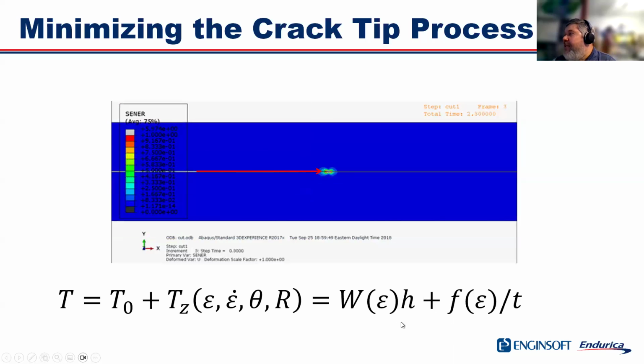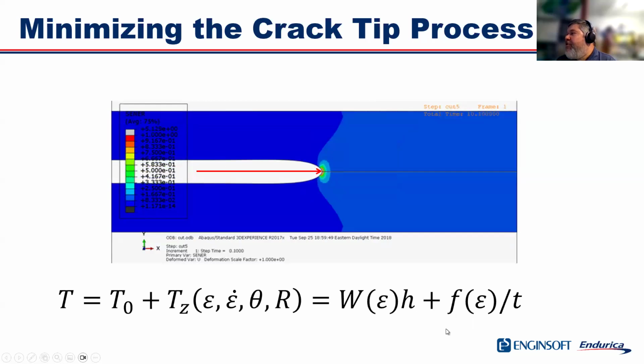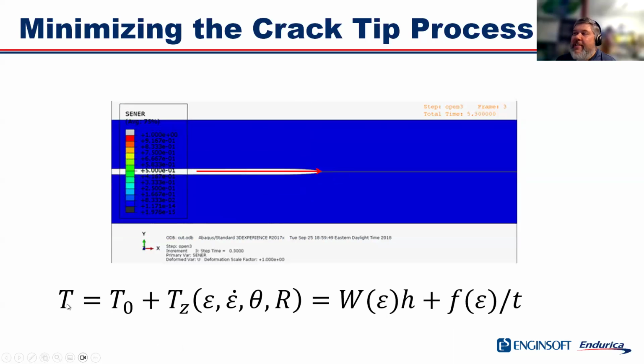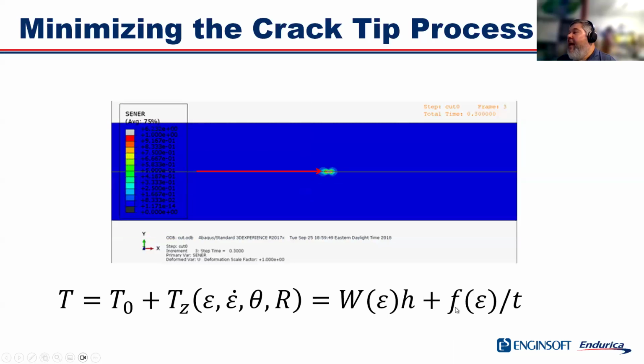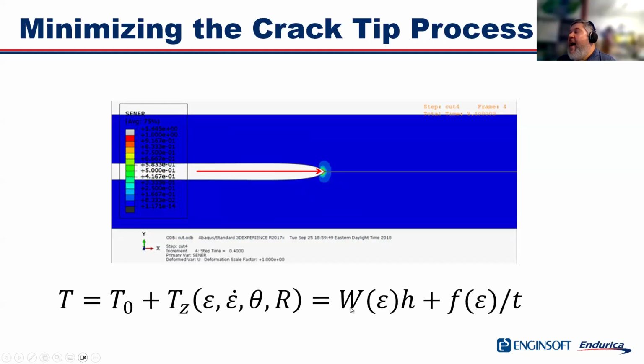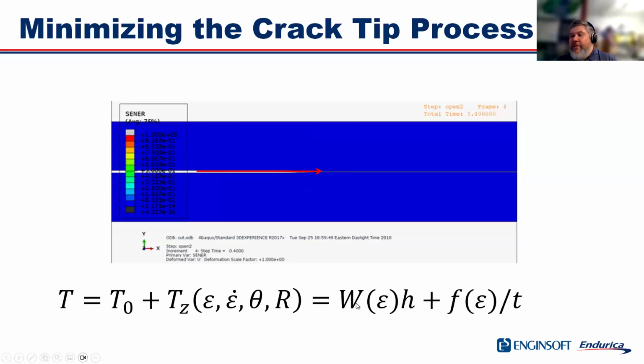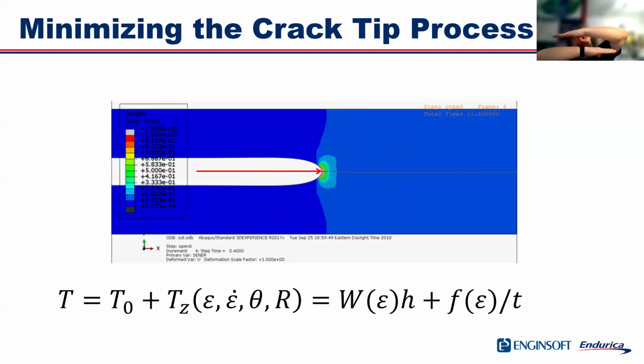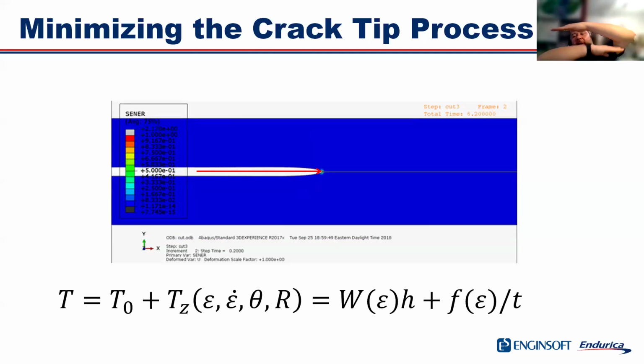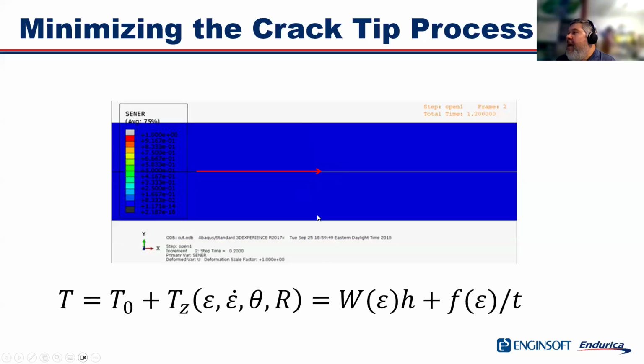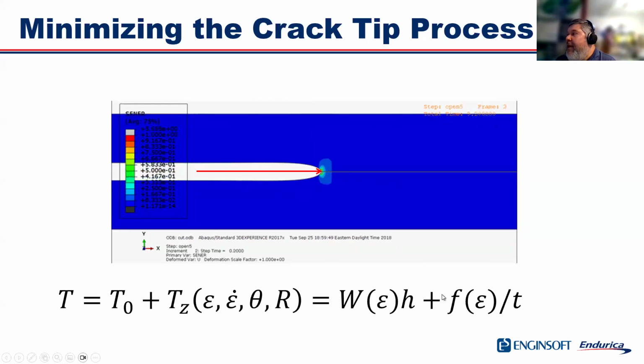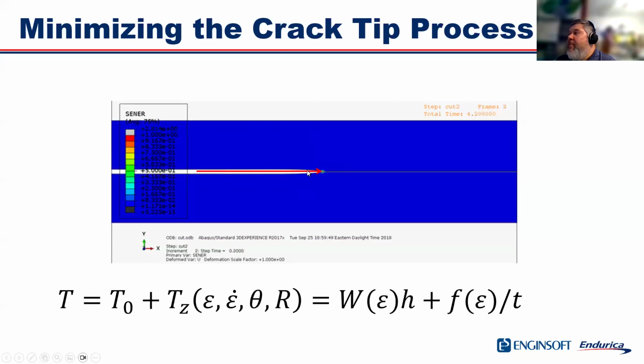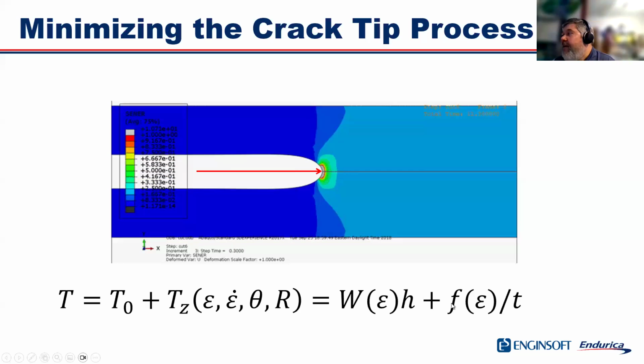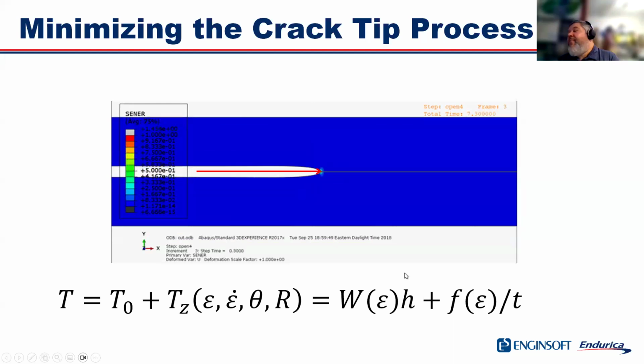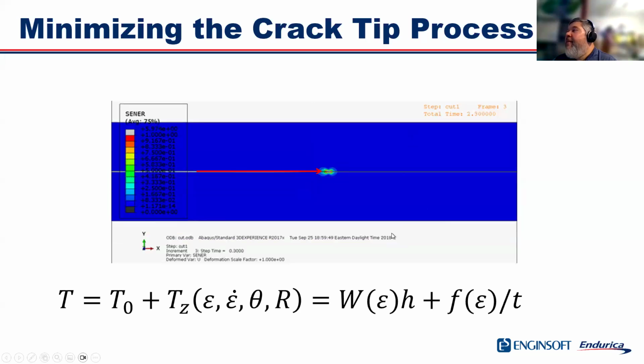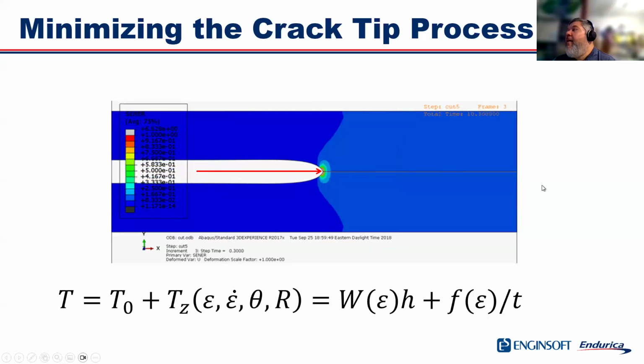Now you'll notice here I've got another equation to the right that's got two terms. This is an equation that expresses the tearing energy in this experiment. The first term is the tearing energy that the crack experiences due to the opening of the crack, right? If I have a crack and I stretch the rubber, there's a certain tearing energy that's happening just because I'm opening the crack. That's without putting the blade on it. And then when I put the blade on, if I know the force on the blade, that's little f, then that contributes an additional energy, and that's the second term here. So the first term is the opening component of the energy. The second term is the cutting component of the energy.